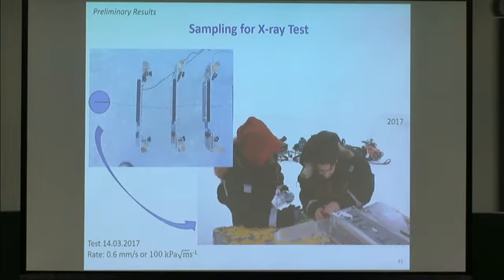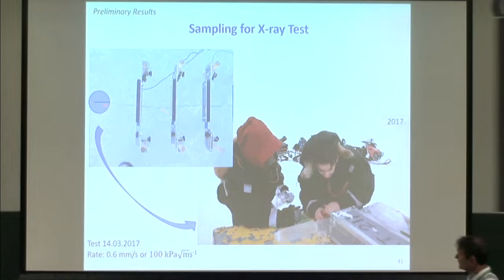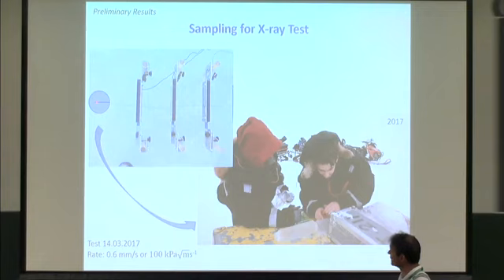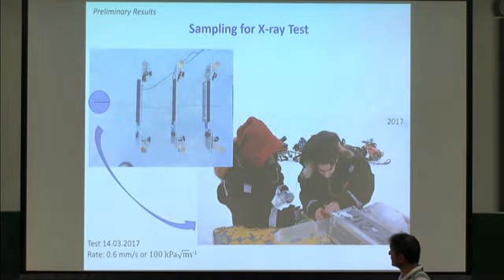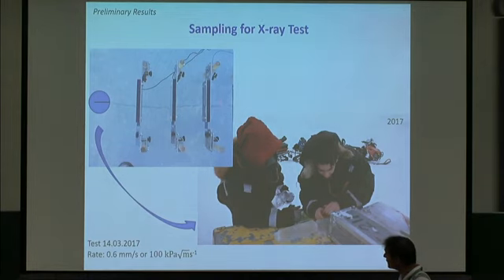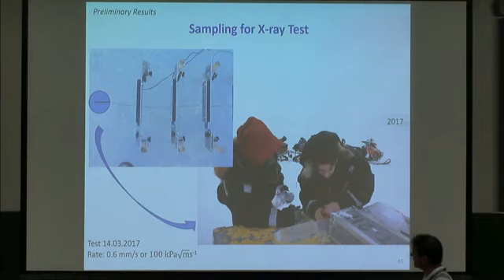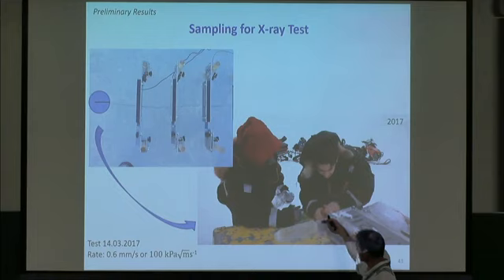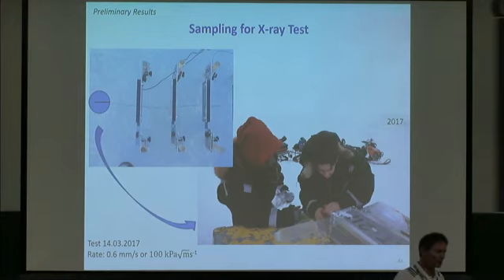So that was about the notch. Yeah. So what you see here now is another core taken from the crack tip, including the crack tip. And you can clearly see this displacement sensor being measured over the crack, and of course also where you have the loading device. For the result you see now in a few minutes, we have a loading rate of 0.6 millimeter per second. And in this case, we have the crack tip included in this core. So it's the core sample we have taken from what is indicated on the photo here.